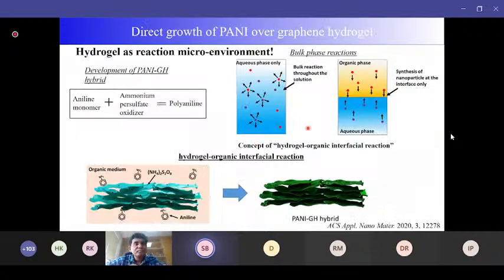In this case, we first checked that we have our graphene hydrogel structure, and because the hydrogel is porous, there is a lot of water trapped within the hydrogel structure. So we considered whether we can use this hydrogel as a reaction medium, because this trapped water can be thought of as a microenvironment. Can we carry out some chemical reaction within the microenvironment? For that, we went to the well-known method of the aqueous and organic interfacial reaction.